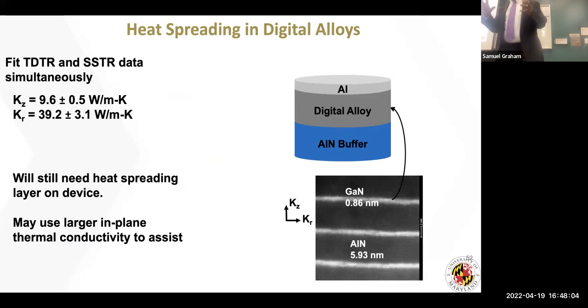This is showing that we can play around with these digital alloy structures, and we believe that we can push the thermal conductivity up as well as increase the thermal conductivity within the plane. That will now build heat spreading into these ultra-wide bandgap devices. This is the first time someone has actually gone through and said, how can I build a structure where, typically, everyone's saying the thermal conductivity is low, and I actually start building these architectures where now I can manipulate the overall thermal conduction through the system. We believe that as you start looking at the closeness of these interfaces, those interfacial modes are actually enhancing the heat transfer. That's just a hypothesis. We still have to go figure that out. But this is sort of what I was trying to get to: engineering the thermal properties of these materials, either by heat spreading, by adding materials, as I showed you earlier, or by going to digital alloy architectures.